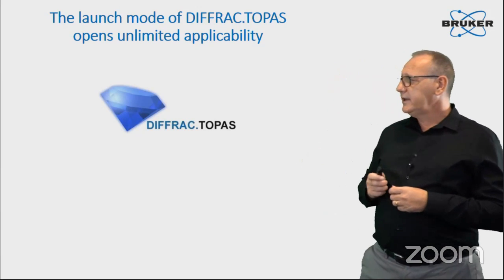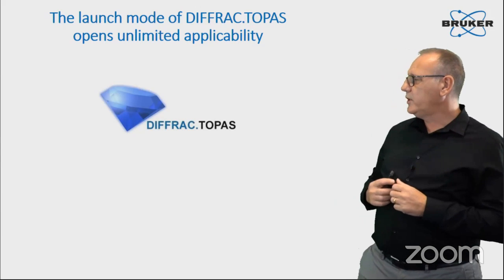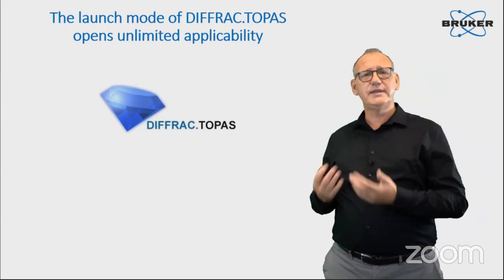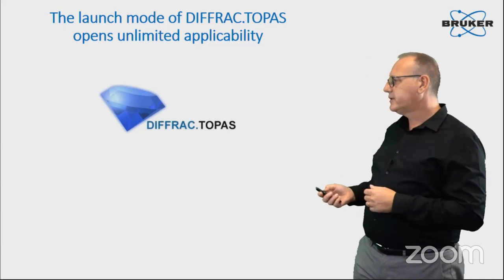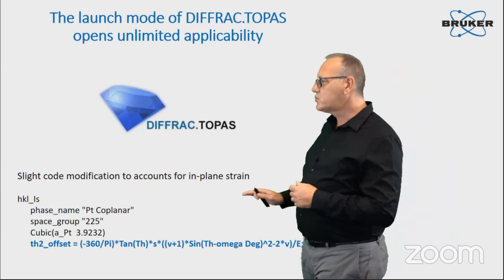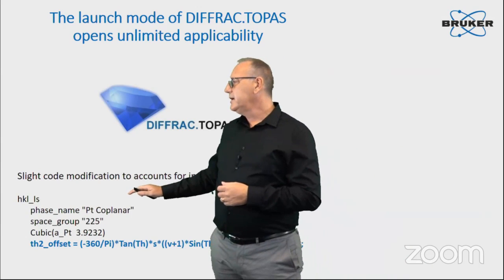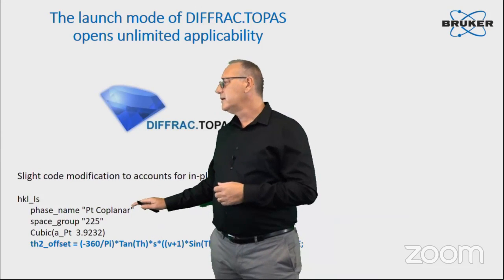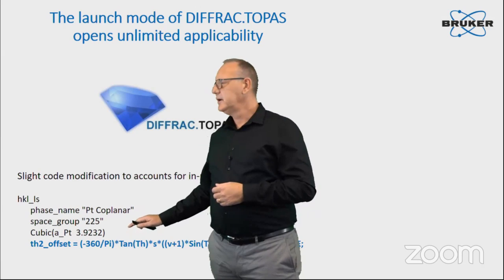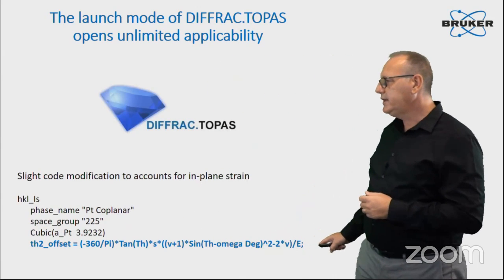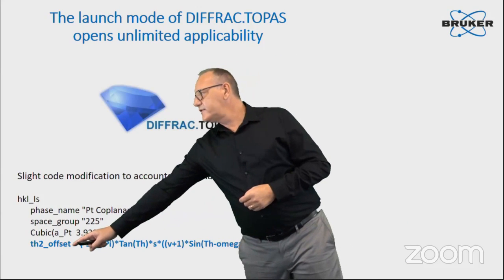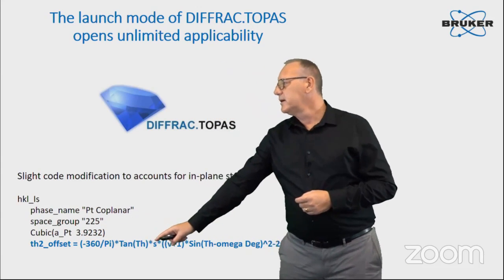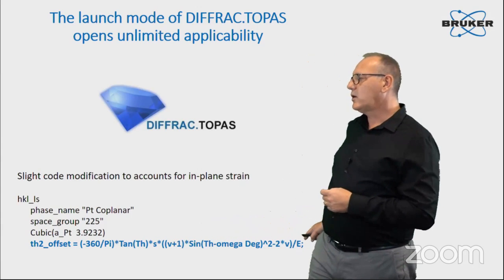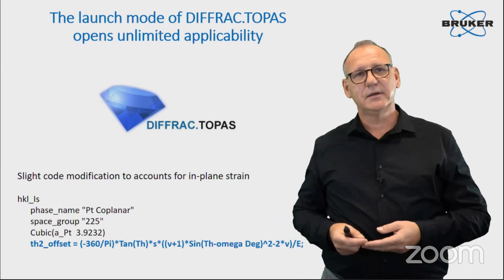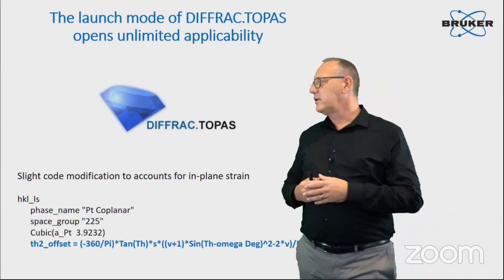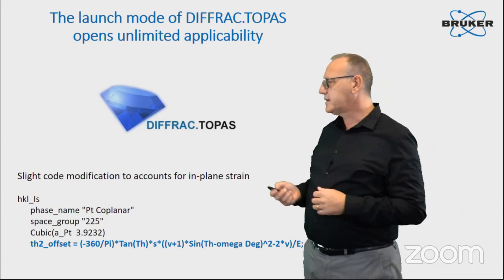But the beauty of Topas is that you can access a launch mode, an editor mode, where you can actually implement the physics you want into your refinement. Without going into the details, but just to show you how simple this can be, this is the original code for a phase with a name, a space group, and a lattice parameter. And just by adding one line in the code here, this is the delta 2 theta we've seen before. This is my 2 theta offset created by the stress, which is here. So with adding one line in the code, I have put the stress theory into Topas. So it gives Topas a kind of unlimited applicability because you can put whatever you want inside.